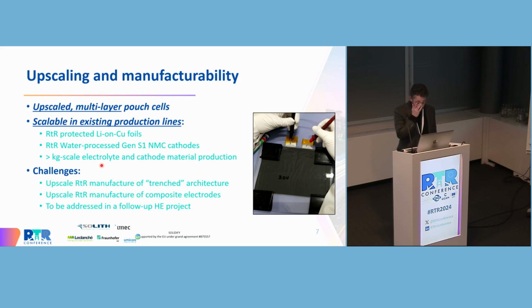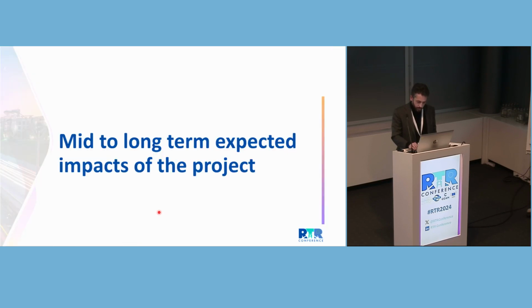However, we are as well facing some challenges which are mostly related to the trench architecture, which is difficult to upscale. Another challenge is due to the impregnation of the electrolyte within this trench architecture. In principle, the electrolyte can be manufactured by doctor blade coating, and we expect some improvements, which perhaps may follow in a follow-up Horizon Europe project.